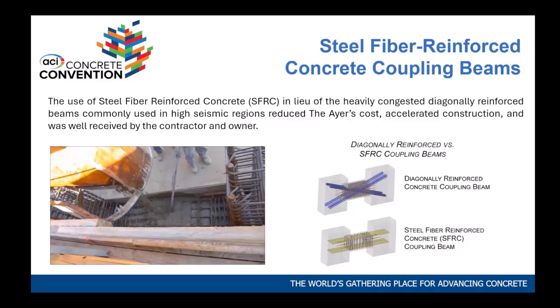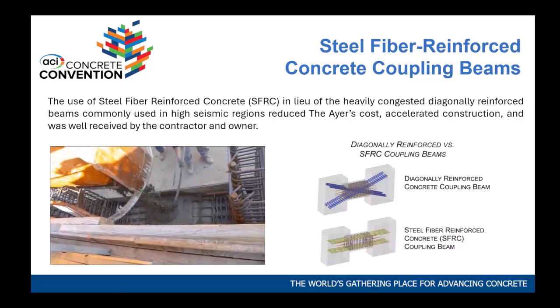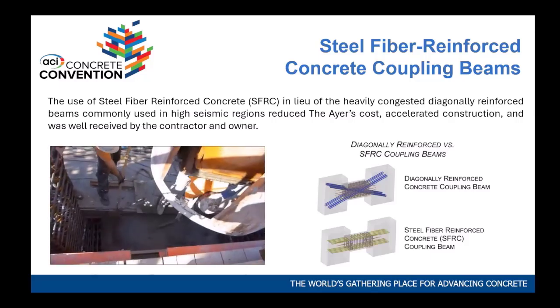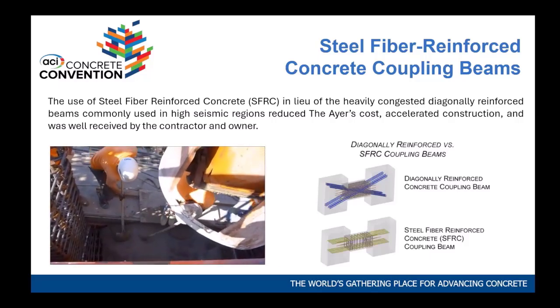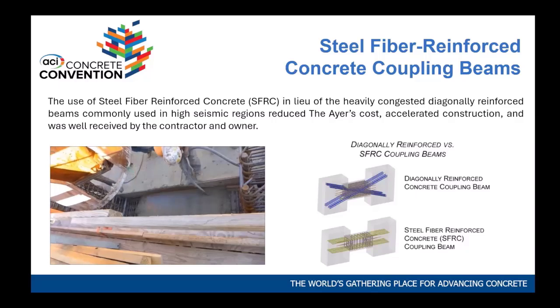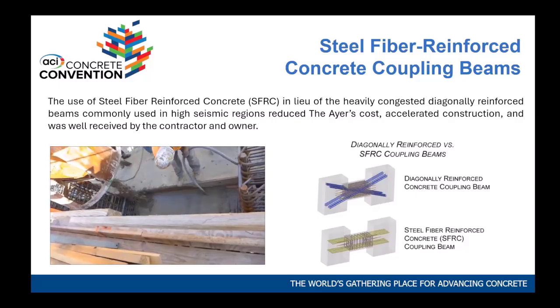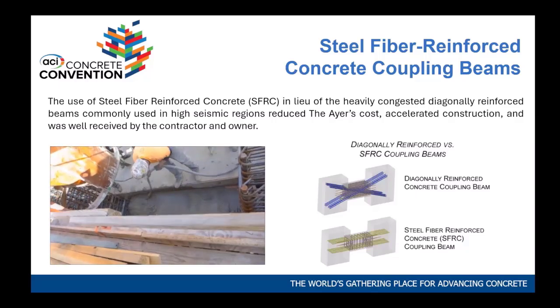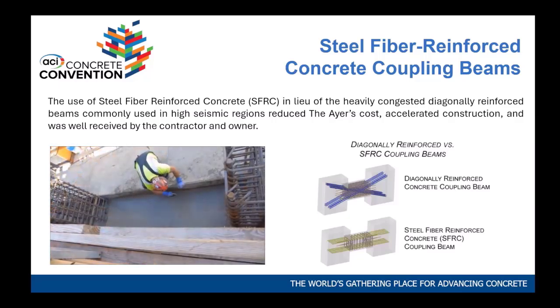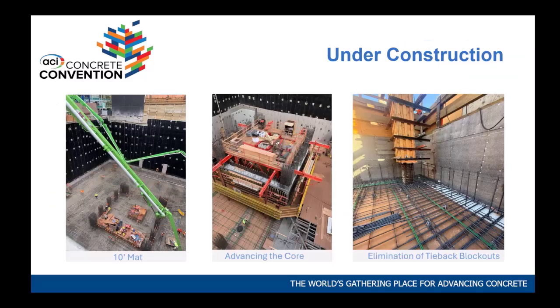It's interesting, we use the SCC mix. When you put the fibers, not because the steel fibers suck water, they don't, but it turns the SCC mix to a 6-inch slump. You have a 27-inch slump for a self-consolidated mix, and you put these fibers in, suddenly you're down to 6 inches, plus or minus. But they're all over the mix, you don't see them when you strip, so it's a pretty neat thing. We've done about 15 buildings like this throughout.